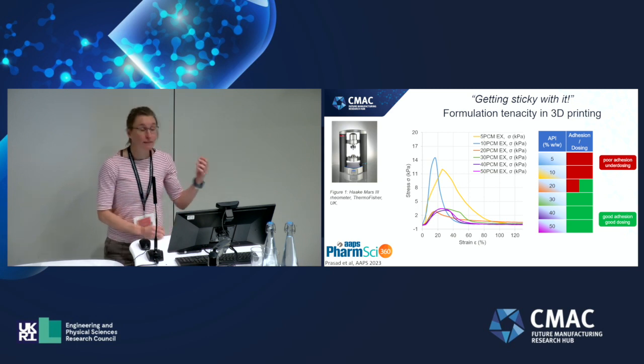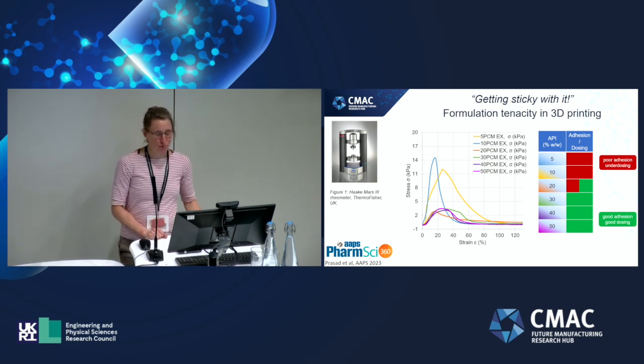So we're actually sticking with the example of the 5 to 50% drug loading of fenofibrate that I showed earlier. When we were assessing the low drug loading formulations, they showed very poor adhesion and also underdosing. And this screening test then allows us to identify or adjust our process conditions accordingly to overcome or prevent this, and obviously speeds up the development process because we know more about the system before we start using it.